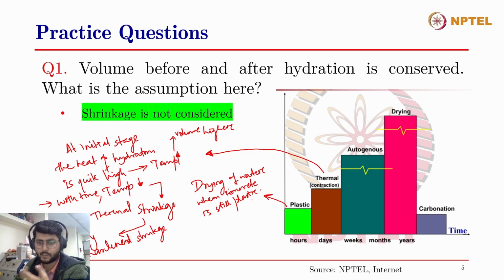Plastic shrinkage also undergoes certain kinds of cracks. You can see it when you have cast a small sample or a cube or some kind of specimen, and if you have left it open without sealing it, open to interact with the environment, certain map cracks are visible on the top surface of the cast sample. This is basically due to the combined action of chemical shrinkage, autogenous shrinkage, and the plastic shrinkage, majorly due to the plastic shrinkage, because the water on top is getting evaporated, so the top layer is trying to shrink, and therefore it is undergoing small cracks on the surface.